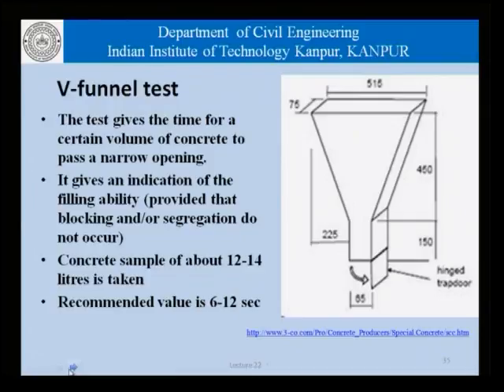Concrete samples would depend upon the size of the V funnel. It could be about 12 to 14 liters, and the time would vary between 6 and 12 seconds. So, if we have concrete filled in this funnel, which measures about say 500 millimeters on the top, has a width of about 75 millimeters here, and a height of 450 millimeters with a constricted region here of about 150 millimeters, what we expect is that the concrete filled in this portion here, there is a lid which when opened allows the concrete to flow through this, and the time that it takes for the concrete to flow through is